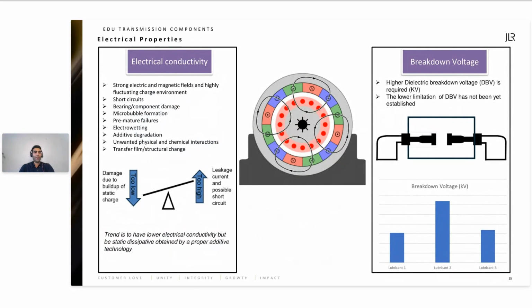In this slide, I would be talking about electrical conductivity. We all understand that within an EDU, there would be high electric field and high magnetic fields. That means that lubricant should be compatible in this scenario, which means we want lubricant to have certain electrical properties. Lubricants should be dielectric, which means it's really important that they have certain electrical resistivity. We want them to have high resistivity, but we don't want the resistivity to be too high, because if they don't dissipate charges, it means that charges are accumulated and lubricant additives are degraded. So that is unwanted. So there is actually, again, a range of electrical conductivity that we would like to see.